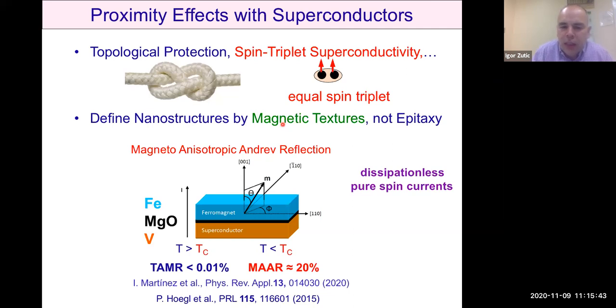And the other one is perhaps more practical. When spin-orbit coupling is present in the system, if it's not strong, usually it can be neglected. So we know that spin-orbit coupling is behind perhaps the first element of spintronics, this so-called anisotropic magnetoresistance from 1857. But there are many systems where in the normal state, spin-orbit coupling is small, and the tunneling analog of this anisotropic magnetoresistance is negligible.